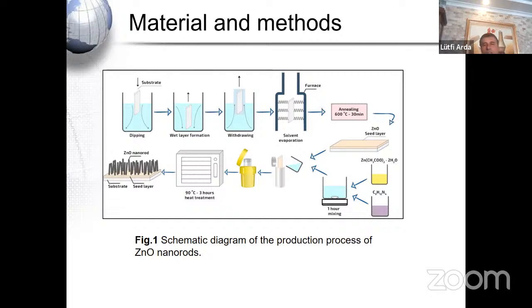How about just the zinc oxide nanorod? We didn't use the glass and the zinc oxide seed layer, just the second part. We put zinc acetate dihydrate and hexamethylenetetramine in the Teflon-lined stainless steel, and then we heat treated this. We get only zinc oxide nanorod.